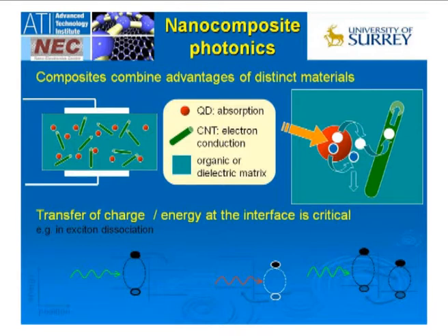What we are doing at Surrey is quite interesting, because we've taken those various concepts and said: let's take an organic material. Let's use a material that we know very well — carbon nanotubes — and start mixing nanotubes with this organic material in order to create our nanoheterojunctions within this structure. We are currently showing that we can come up with cells that are close to the state-of-the-art, and what we need to do is improve the efficiencies of our organic materials in order to enhance the dissociation rate of the excitons.